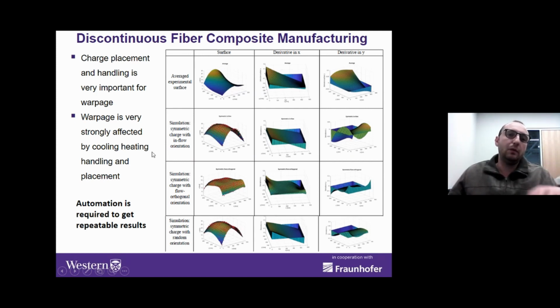And the reason is because things like warpage are extremely sensitive to initial conditions. And when you're doing the work manually, it's very hard to know what the initial conditions are, if you need to know them accurately. So this is where, again, automation is required to get a repeatable process. So right now what we see in the discontinuous fiber parts is that when we make the parts and when we test them in mechanical properties, we see quite big deviation from part to part. And so when you design a part, you have to design it much heavier than what it should really be in reality.